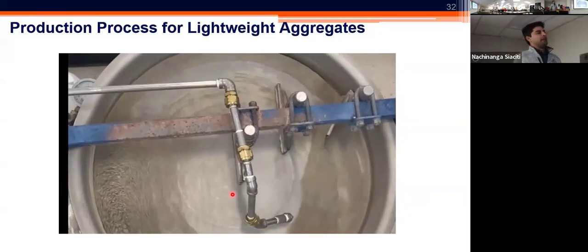We know that the big pelletizers in the large scale need to only operate for 3 to 4 minutes. We call this time the retention time. So your material will need to be dumped into the pelletizer and exit the pelletizer after 3-4 minutes. Our process currently lasts about 30 minutes, so we need to do more work to improve this process. But at least the fundamentals are there where we can see the production of the lightweight aggregate in that sense.